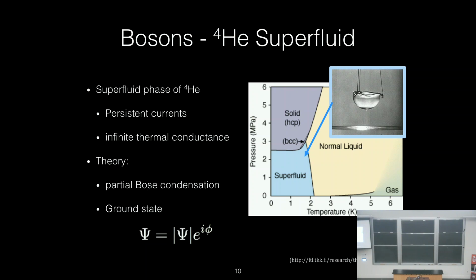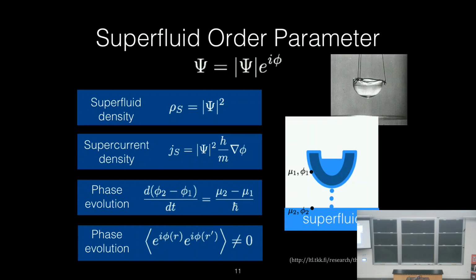The way we understand those properties is to say, okay, there's a partial Bose condensation where a lot of the helium atoms enter what you might call a single quantum ground state. It's characterized by two parameters: the amplitude and the phase of the order parameter. Here's that superfluid order parameter. You square that amplitude, you get what we call the superfluid density, the amount of fluid that can flow without viscosity. If we want to understand how that current flows, what we have to know is how that current density changes when we change the phase in space. So if you create a phase gradient in the order parameter, you actually get a supercurrent.